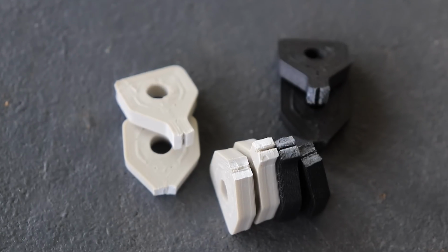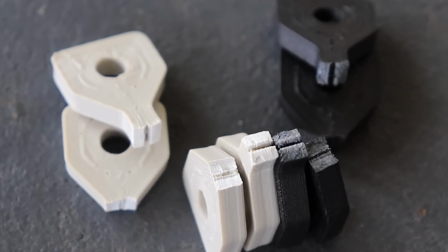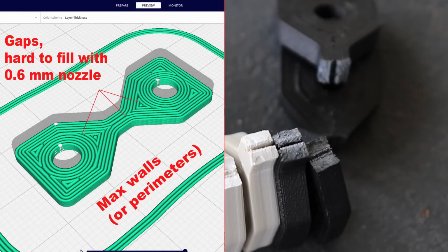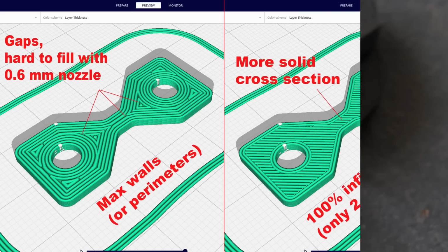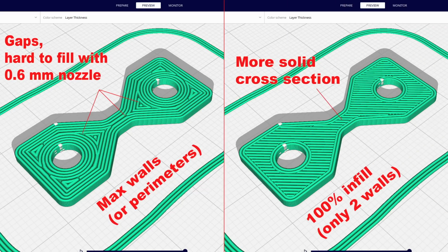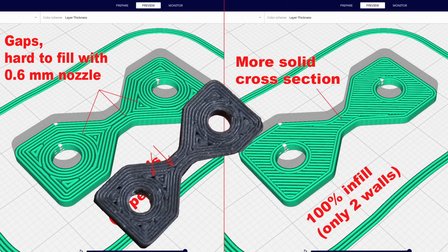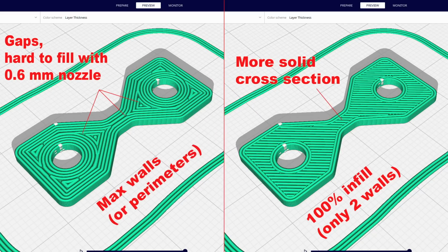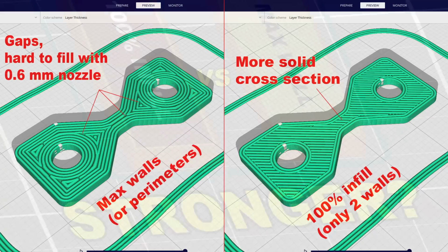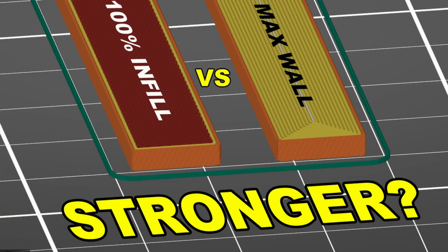If we take a closer look, we can see a small gap at the break point, and this may be the disadvantage of the 0.6 nozzle because it cannot fill all those gaps. That's why, using 100% infill, I noticed that it's better than the maximum number of perimeters. But this is my testing method, so I will not change this. But for mechanical parts, 100% infill is better than the maximum number of perimeters. This I measured in a separate video.